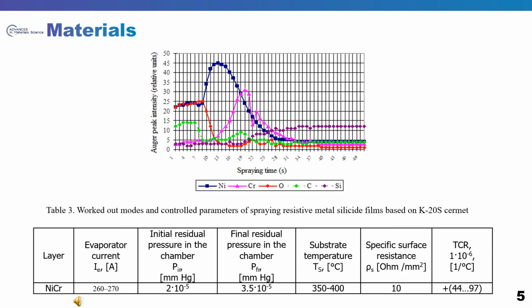The alloy has proven itself in the best way as resistive films based on nichrome. In the case of correctly selected sputtering modes, thin film resistors based on nichrome have a positive TCR sign lying in the range from 44 to 97 ppm/°C without preliminary annealing and temperature adjustment.